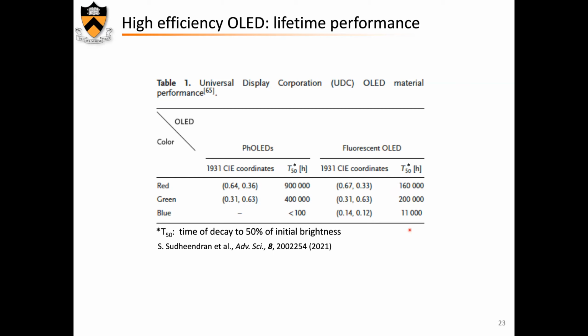Blue is always difficult because, of course, the bandgap is larger, the energies involved are larger, and that leads to faster degradation. For the PHOLEDs, there is considerable improvement for the red and green, not the blue, and therefore most of the applications use PHOLEDs, green and red, and fluorescent blue. But as you can see, the lifetimes of these things are now considerable, and that is, of course, very good news for applications such as displays and others.